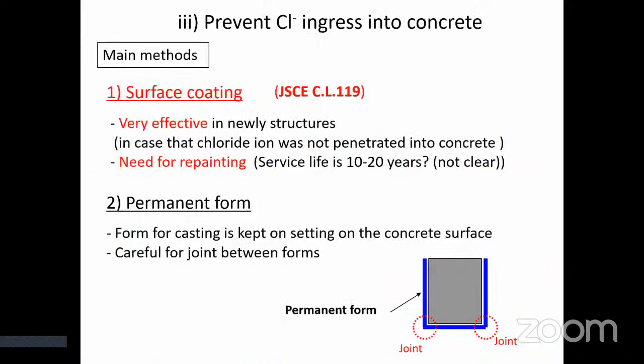Next one is preventing chloride ion ingress into concrete. The main method is surface coating. This is very effective in newly built structures. However, repainting is needed because the service life is 10 to 20 years.